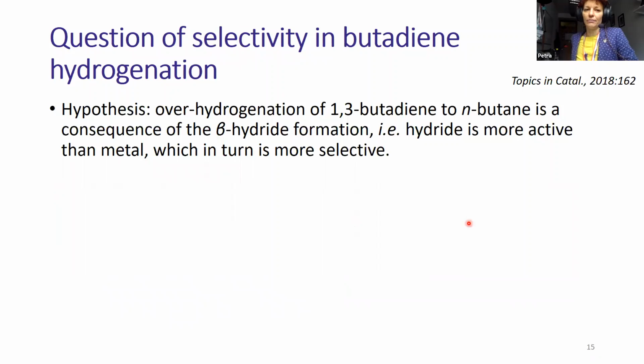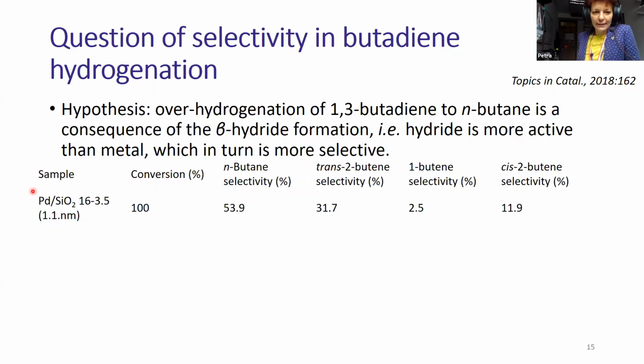So there was a hypothesis in the literature, as I mentioned, that the over-hydrogenation is a consequence of the formation of the beta hydride, the interstitial hydride, which is more active and less selective than the metallic phase. So here is an example in which palladium particles were deposited on silica. You can see that they're about 1.1 nanometer diameter on average, which is comparable with what we had in our system. And already you can see that they had over 50% n-butane formed. Now in our case, that was only around 10%. So in our case, of course, when the palladium was confined in the pores of the metal organic framework, this was to a much lesser extent.